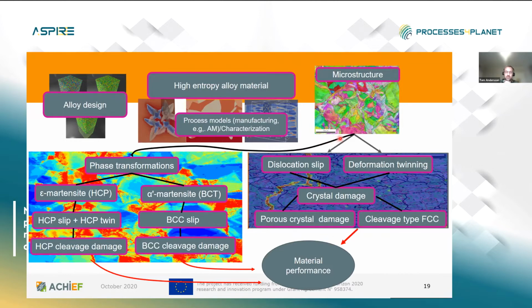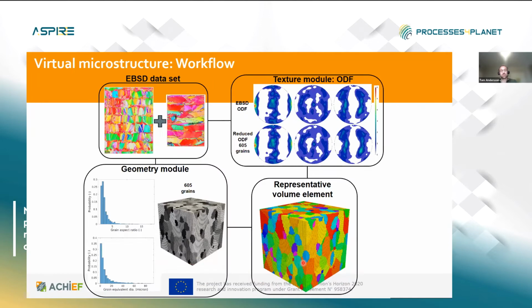predicted deformation mechanisms, we apply this crystal plasticity model to get the behavior and ultimately the material performance of the material. So here is the example of how we are going to do that. Basically we have the characterization data, we take the orientation distribution from that and create this synthetic representative volume element. So this kind of representative material block has the same orientation distribution as the real material. And we use that for this crystal plasticity analysis.